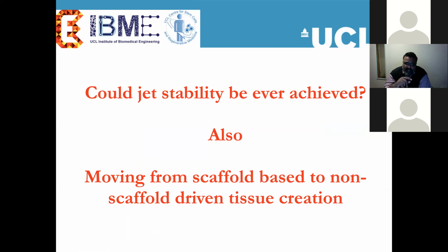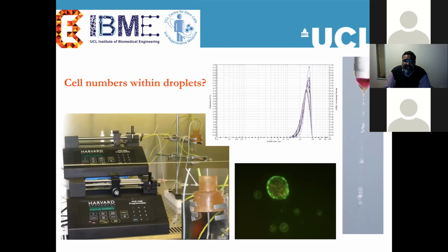So the problem that I showed you before is, although we are able to spray the cells, because the actual cell solution has a high conductivity, the cells spray in an unstable mode. So we went back to the literature, and we found that you can put one needle within another, a coaxial needle. You can see that the inner needle has a red liquid.